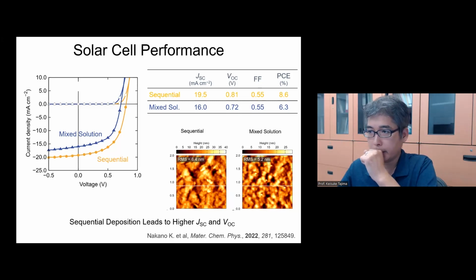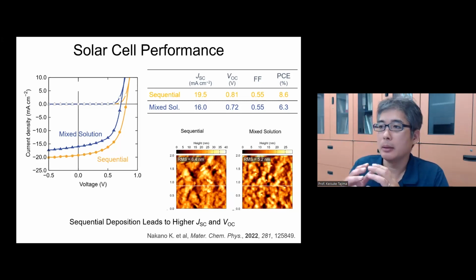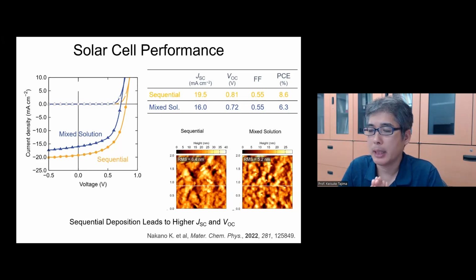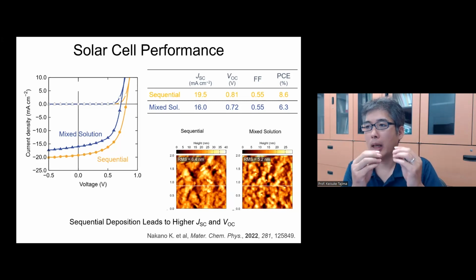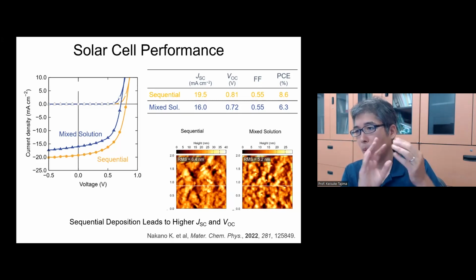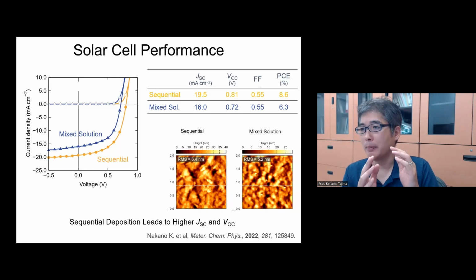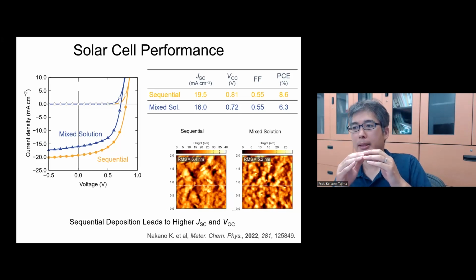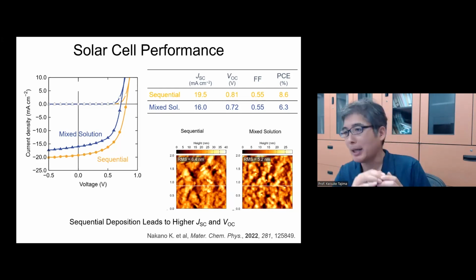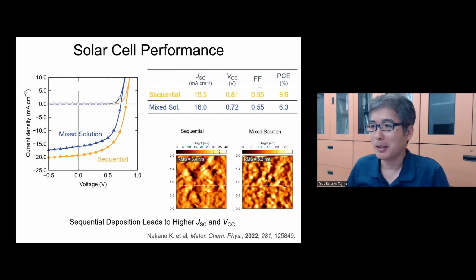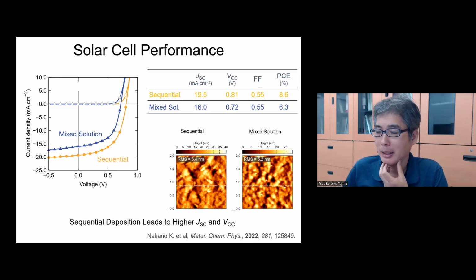Yeah, that's a good question and a tough one. High crystallinity in general is good for the charge transport, and optical property is often better with high crystallinity. So high crystallinity is preferred, but at the same time, if you start to have small crystals inside the film, the orientation of each domain is very difficult to control. So I would say the best case is, of course, both high crystallinity and orientation, and that will give you the highest performance.